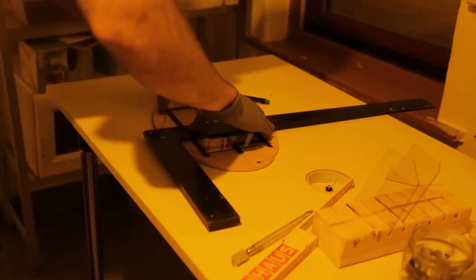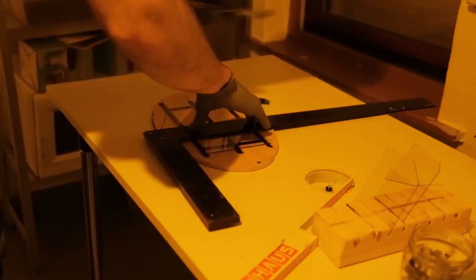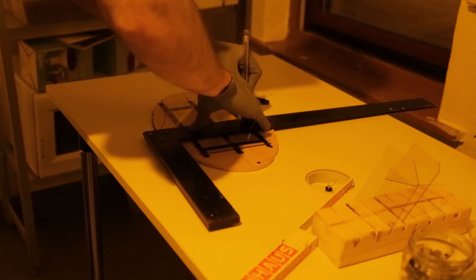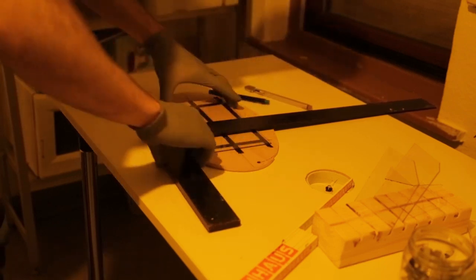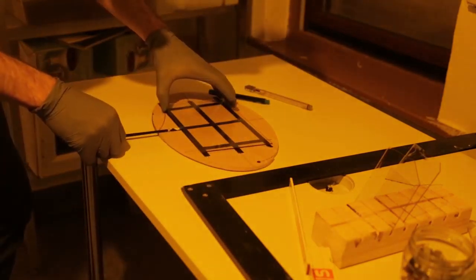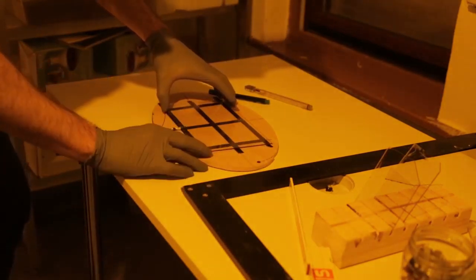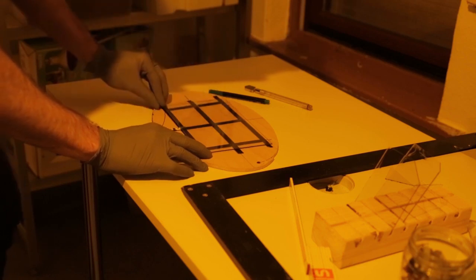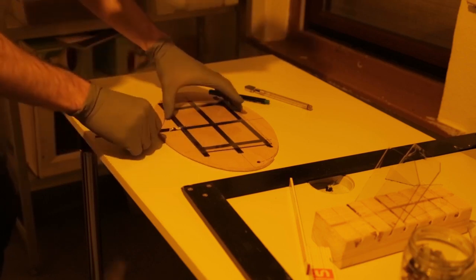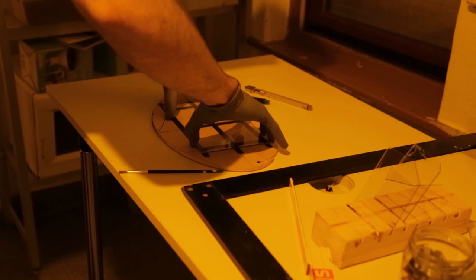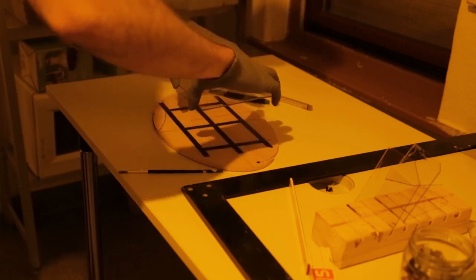I've prepared a little board to assist me in cutting the plate into 4 separate pieces. On the board, I've glued strips of duct tape that act as spacers for the cutting job. Without the duct tape, the glass would break in undesired areas during cutting. The emulsion side touches the duct tape and gets damaged by it. But as long as this is happening only on the outer perimeter, that's okay.